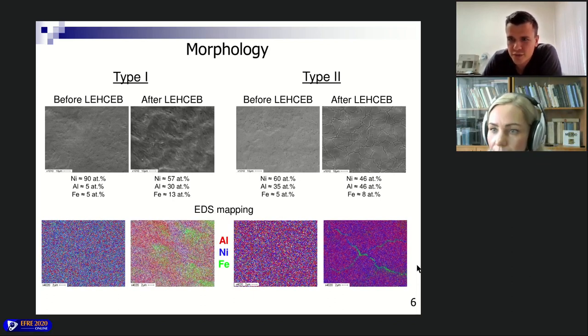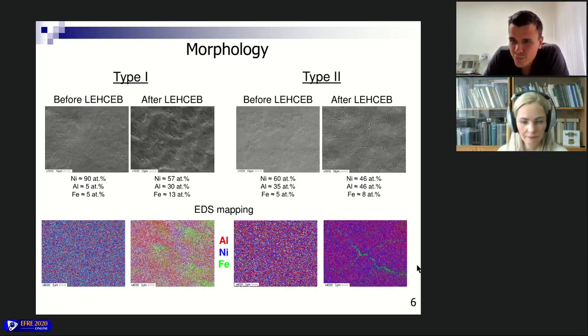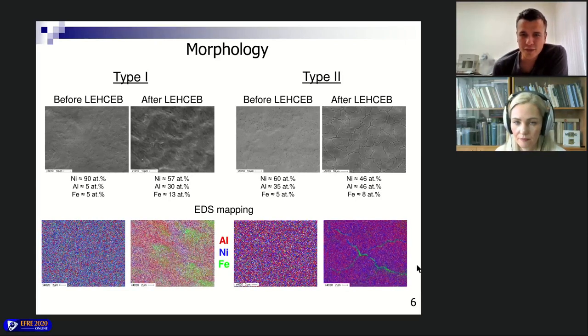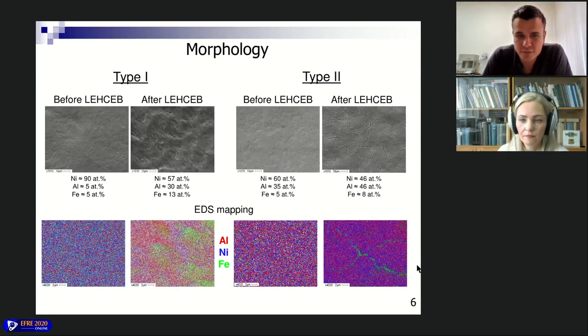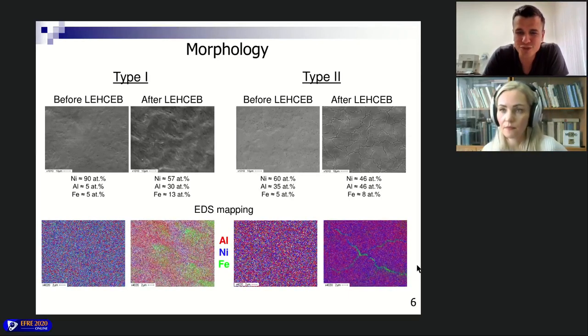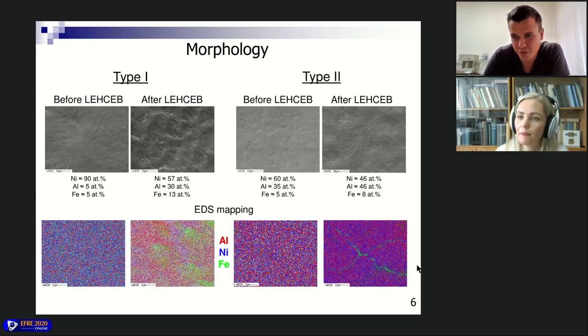My question is about slide number 6. The EDS map: what is the cause of cracks that are filled with iron? These cracks are a result of the formation of a brittle phase of nickel aluminum intermetallic on the non-brittle stainless steel. About the high quantity of iron inside these cracks, I will discuss it with my colleagues and we will answer you a little bit later.